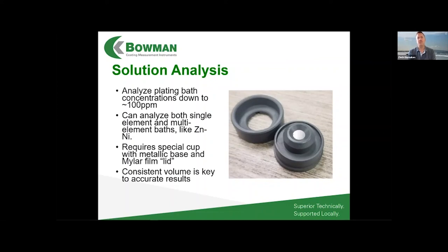And you can do that with XRF as well. This has become more popular over the years, because if you're getting an XRF for measuring plating thickness, then you might as well measure the plating solution as well. What I've got here is a picture of our solution cup. Since we're measuring from the top down, it gets a little tricky to measure solutions because we want to have a consistent volume that we're presenting to the X-ray beam. So what we do, on that little piece on the right, is put a few drops of solution onto that little shiny metal plated surface. It creates a reverse meniscus, sort of a bubble.